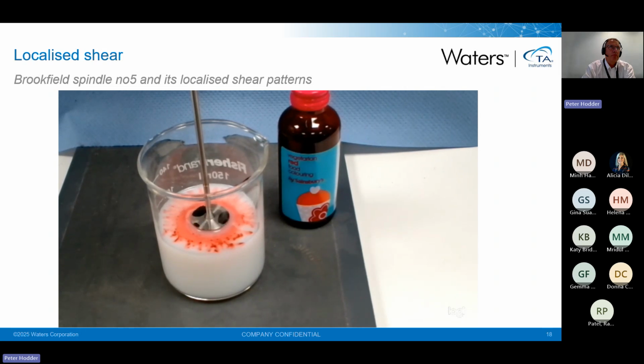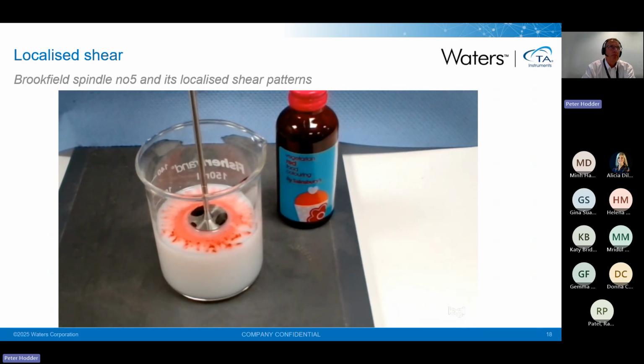If I decided to try and change the speed, so we're going to turn the speed up. It's clearly going faster now. Then again, you can see that the field will perhaps change slightly. That white band will expand ever so slightly. But again, we're not really certain how much of the sample we're stirring. And we're certainly not stirring the whole of the beaker.